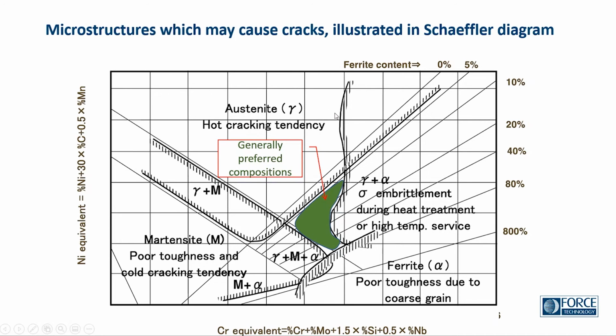By that, we can calculate a position in this diagram for a composition welding one material or welding several materials together. And if we're in this area where we have the full austenitic solidification, the risk is that we could get hot cracking. And in this part over here, where we have low chromium and nickel equivalents, the risk is that we get martensite, which is a hard but brittle structure. In the full ferritic material, we experience poor toughness due to grain growth during the welding process. So we don't want to go there either.